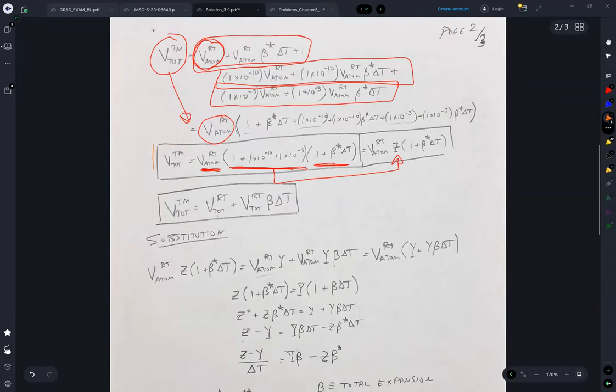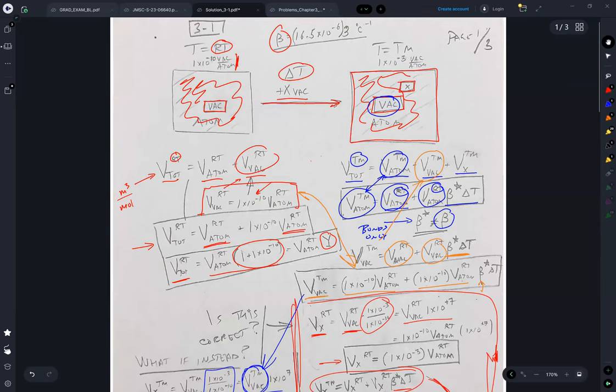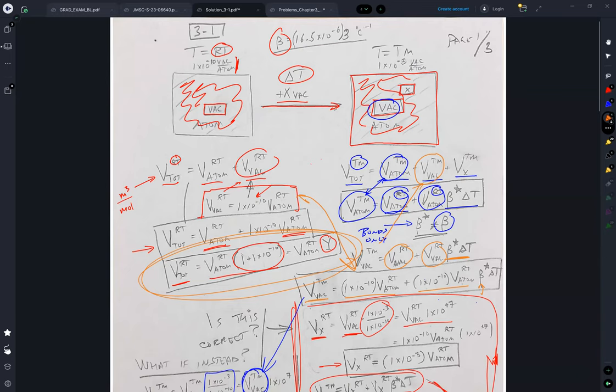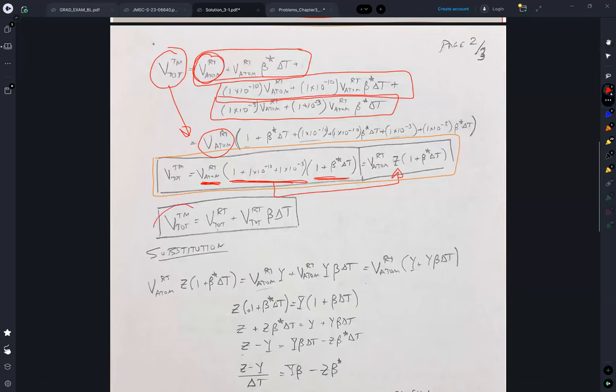Okay, so I now know the total volume at the melting temperature in terms of the volume of the atoms. And lastly, I know the volume at the melting temperature in terms of the total volume at room temperature using that volumetric thermal expansion — so that's beta, not beta star.